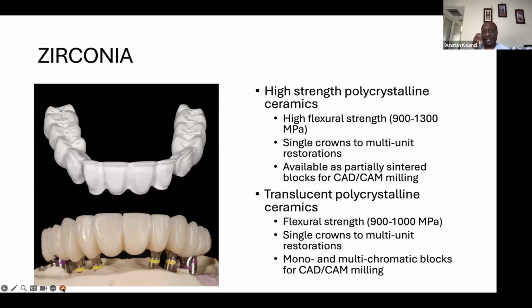So the high strength ceramics have a high flexure strength of 900 to 1300 megapascals. They can be used for single crowns or multi-units. And they, of course, are available as partially sintered blocks for CAD/CAM milling. The translucent has a high content of yttrium. The major drawback of polycrystalline ceramics is that they have high strength but low translucency, which is a major drawback for aesthetics or for anterior crown and bridge work.